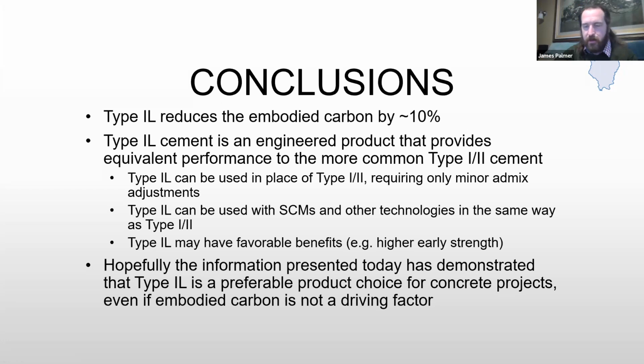I can answer this. Typically, your admix dosages will change slightly. In the trial batches and work that we've done with some of our customers, typically the water reducer dosage does go up slightly when switching from your type 1-2 to your type 1L or PLC. So there may be a slight increase, but at the same time, you're still using the same products in the mix. So it's just an admixture adjustment. And frankly, your concrete producers will be making adjustments daily based on weather conditions and other factors as well.